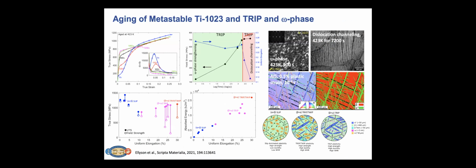So the last example I'll highlight is now going to the mechanical properties of Ti-1023. This is actually on wrought processed material now. In addition to transformation-induced plasticity, when we cool from the high temperature and we retain the beta phase, we also form an omega phase, that's an athermal phase, and that can evolve with aging. So shown here is stress versus strain, and we can see in blue our as-quench condition. If we age these microstructures, we get this massive increase in yield strength, over 4 times, and we're also able to have good ductility as well. So again, summarized here, a massive increase in strength while retaining good ductility.